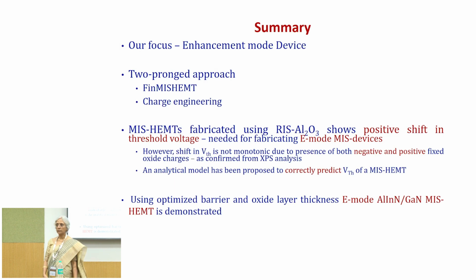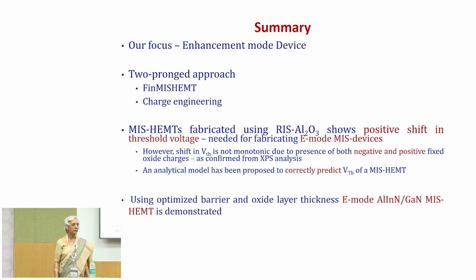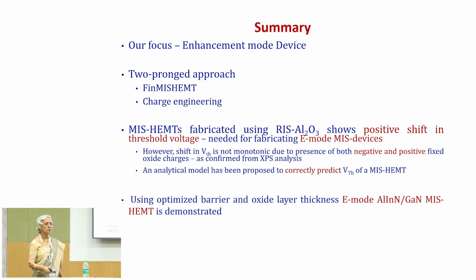So, finally, to come to the summary of our work, our focus is towards realizing enhancement mode devices, and we have tried two approaches. One is that of fin MISHEMT and the other one is that of charge engineering. And these MISHEMTs that I showed you with aluminum oxide gate dielectric, here the aluminum oxide was deposited by reactive ion sputtering, and that showed positive shift in the threshold voltage, which is obviously exploited for E-mode MIS devices.